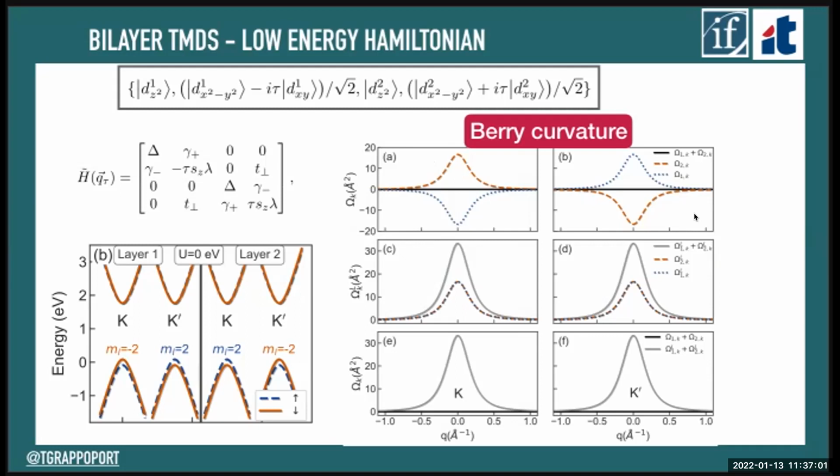If we calculate the LZ projected Berry curvature, as I was presenting in a previous slide, what we see is the two Berry curvatures are finite. If we sum this and calculate the total orbital projected Berry curvature, this is a finite number. And this is why we can see a nice plateau when we integrate this and calculate the orbital Hall effect.